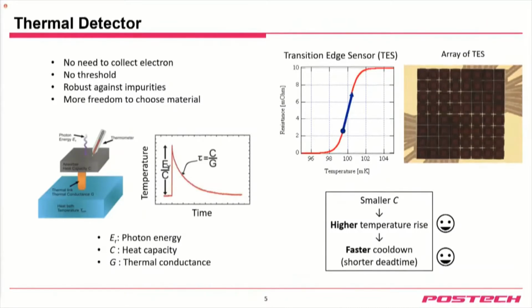So far, people have been using this thermal detector scheme where, when the absorber absorbs the photons, it increases the heat, increasing the electron temperature or phonon temperature. By increasing the electron or phonon temperature, it will change some property of the material itself. Then by measuring the change of the material, we can infer whether there were any photons or not. For that, we need a very, very small heat capacity of the material, such that even if we have a very small energy input, we could anticipate a very high change of temperature. Then we will be able to measure some change of the system much more easily. So smaller heat capacity is a very important parameter that we are looking for.